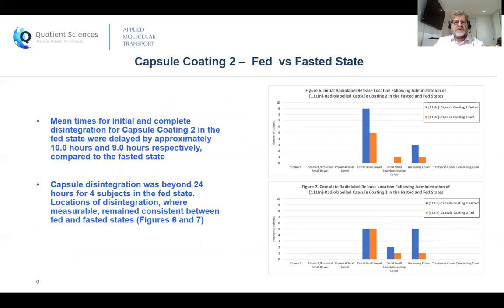Although for 7 subjects where GI location of release could be observed, the locations were the same whether fed or fasted, indicating that the pH-based dissolution of the coating system was performing robustly and worked despite prolonged GI transit times in the fed state. Gamma scintigraphy in this study was up to 24 hours, and at that point, 4 subjects in the fed state didn't yet have capsule release due to the extremely elongated GI transit times. And as such, any gamma scintigraphy monitoring of fed dosing with this formulation system in future would be recommended to continue to around 48 hours post-dose.